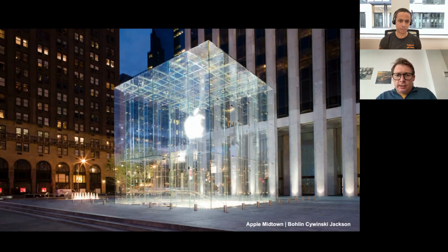And that's because the interlayer is really acting as a catenary or a tensile bridge across the glass. Although the glass is shattered and broken, it's still acting in a compressive manner. So adding a great level of resilience. And so this led us to build some very exciting structures. So I'll run through a few of them now.